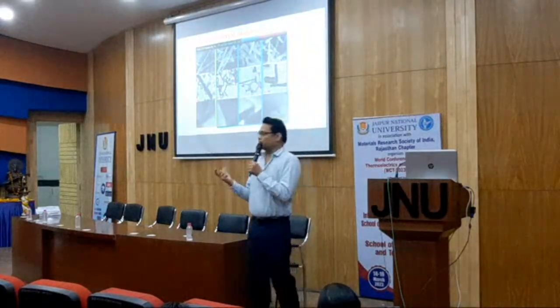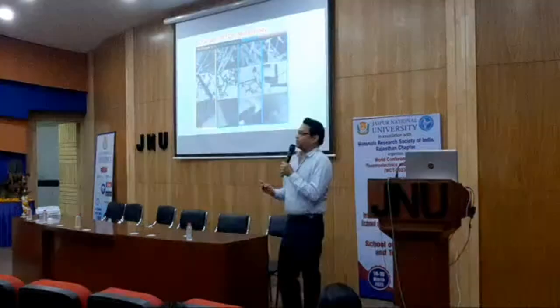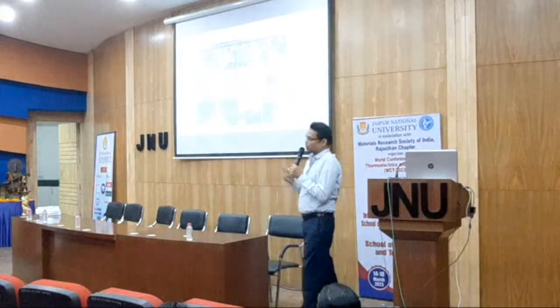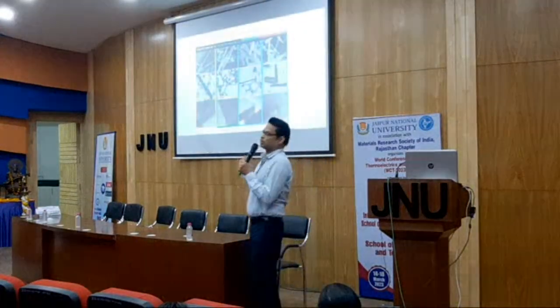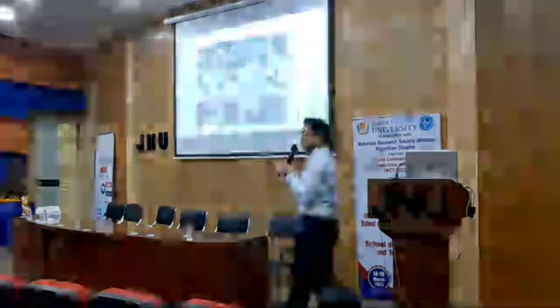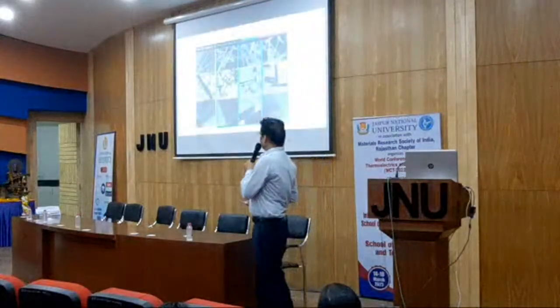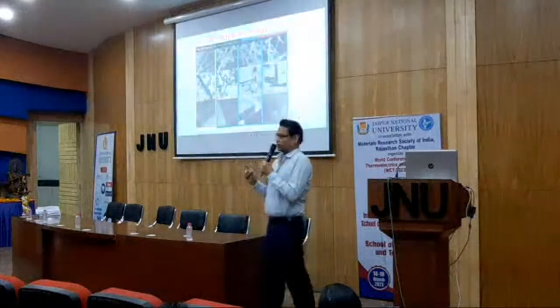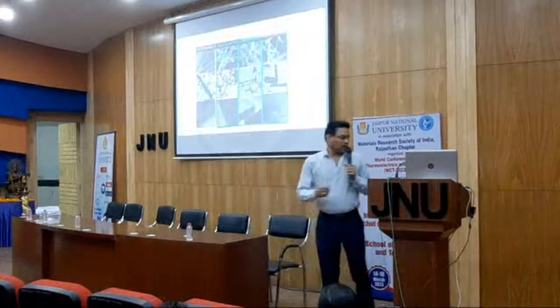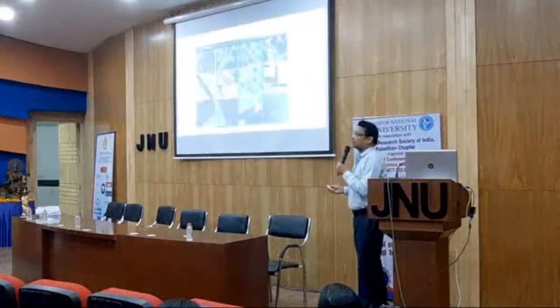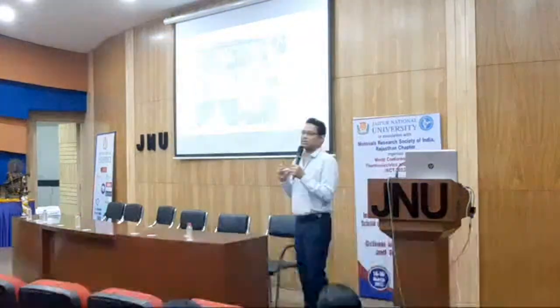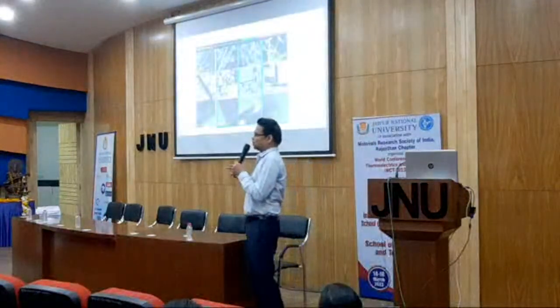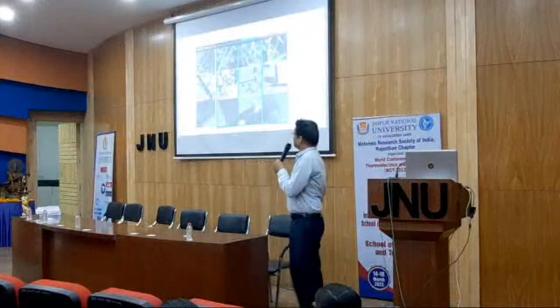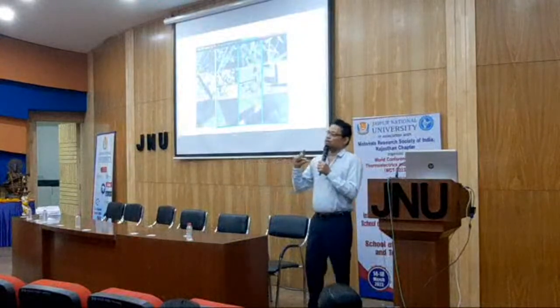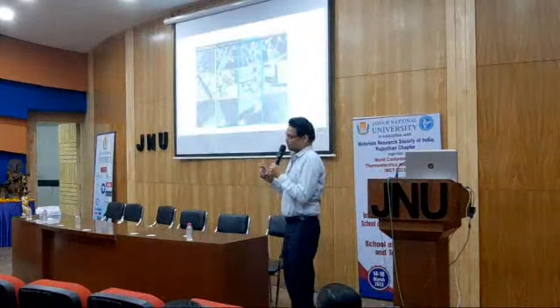You can coat this on a smartwatch or the back of a laptop. These are very flexible. I'll show you how to fabricate this, very simple. You can do it in your lab also, right? Not requiring any costly instrument. And after confirming that we obtained the 3 different morphologies successfully by the synthesis approach we are applying, now we utilize this to fabricate the thermoelectric devices, which is called a thermoelectric generator, by a simple approach.